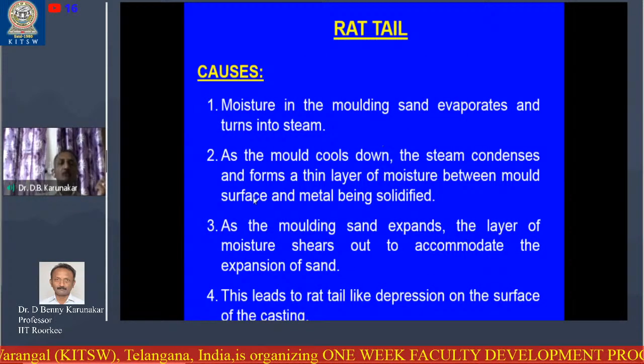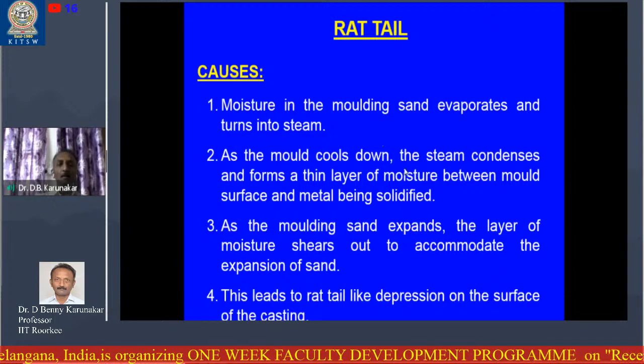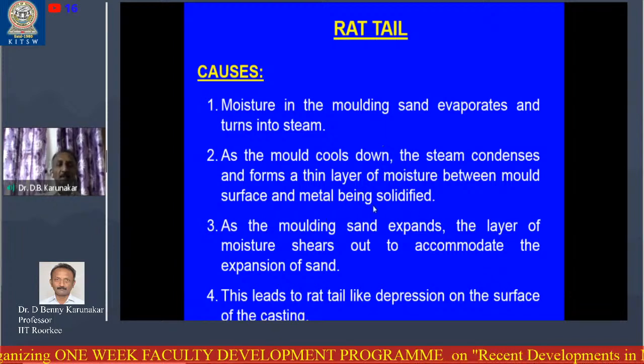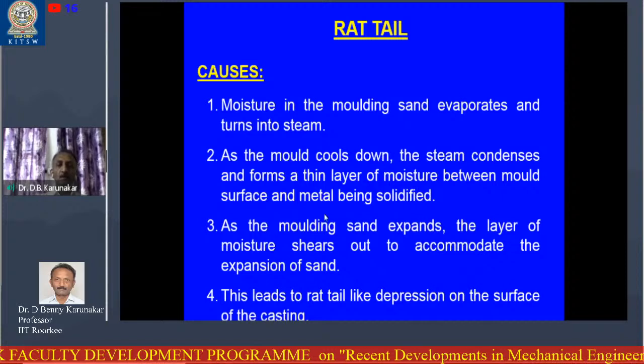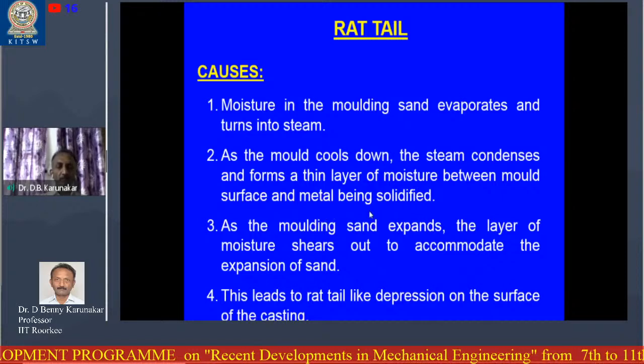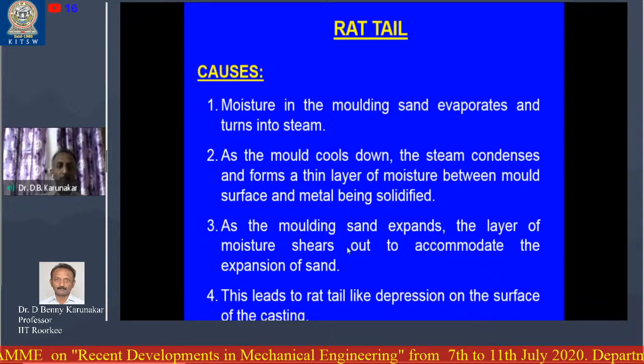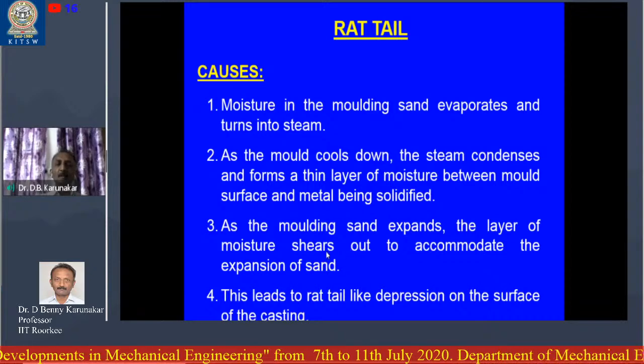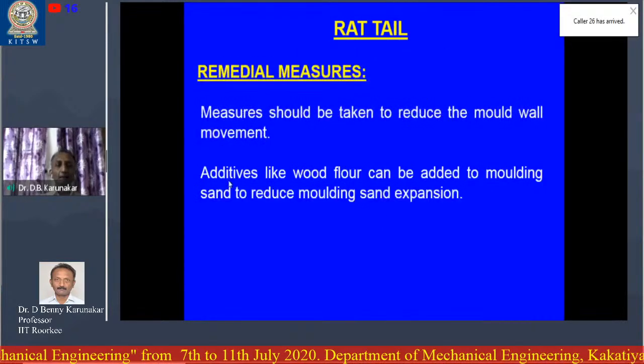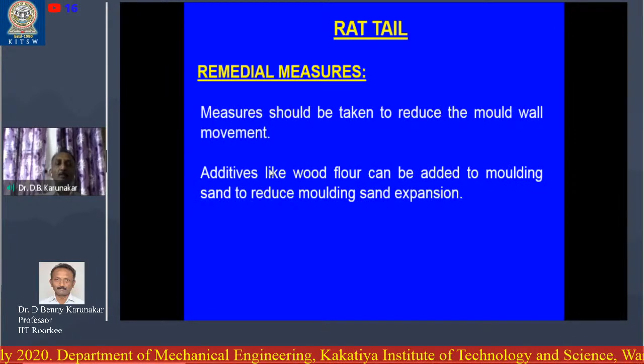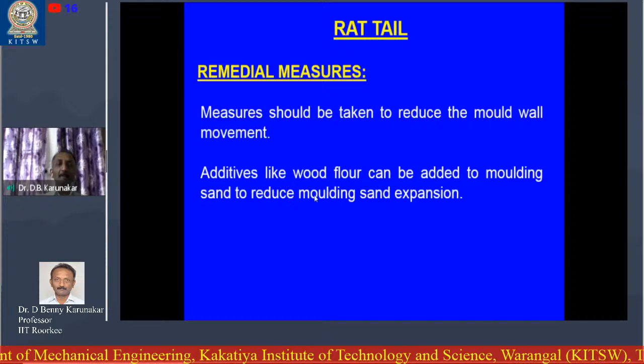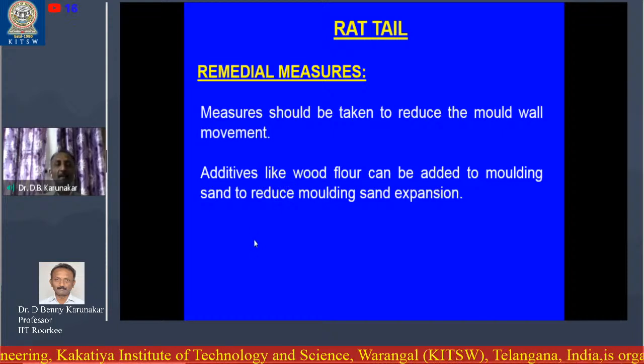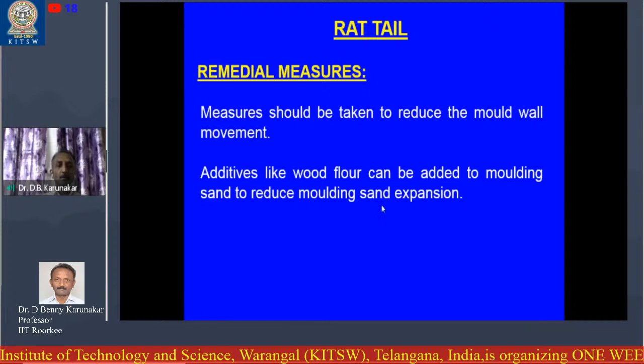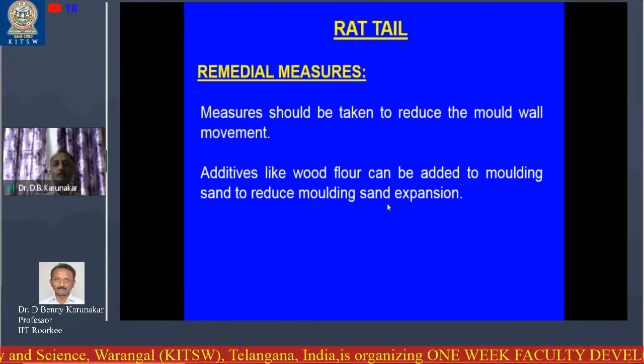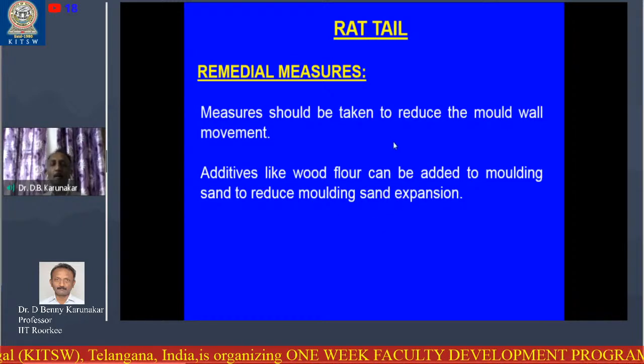Moisture in the molding sand evaporates and turns into steam, and this steam forms a thin layer between the mold surface and the metal casting being solidified. Finally it leads to a defect like a rat tail. What are the remedial measures? Measures should be taken to reduce this defect - additives like wood flour can be added to the sand to reduce the mold sand expansion, since this defect arises due to molding sand expansion.